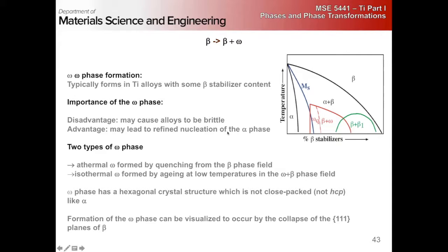It can form either athermally or isothermally, right? And there's just been some really nice modeling work, actually, on omega phase where they looked at the different slip systems potentially there, and the best estimates seem to be that omega titanium, the easiest slip system, has a critically resolved shear stress of significantly more than a gigapascal, right?